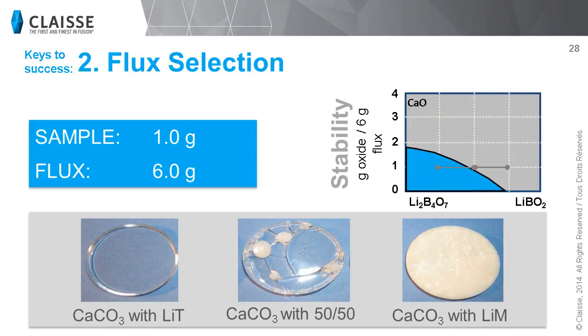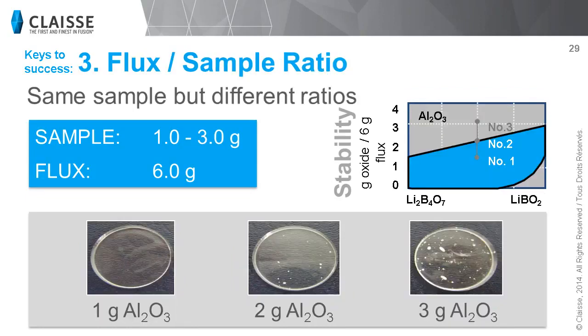So you can see that the right flux to dissolve an aluminum or a calcium sample isn't the same. In an ideal world, each sample type would have its own flux to obtain the best possible result regarding the dissolution of the sample. This principle also applies to borate fusion for solution. If your sample isn't well dissolved in your flux before you pour it into the diluted acid, then you won't get a complete dissolution. The flux to sample ratio is also an important factor to take into consideration when developing a fusion method.